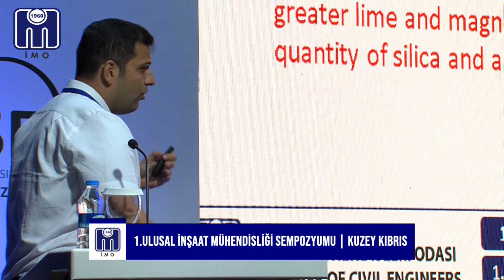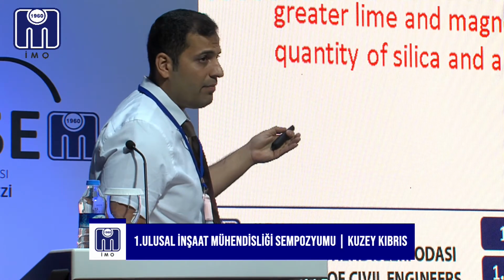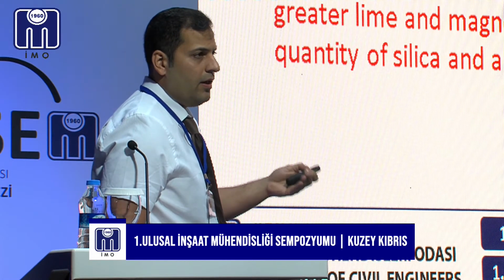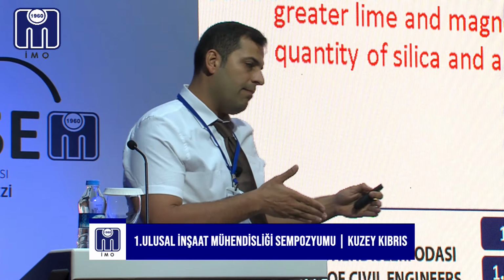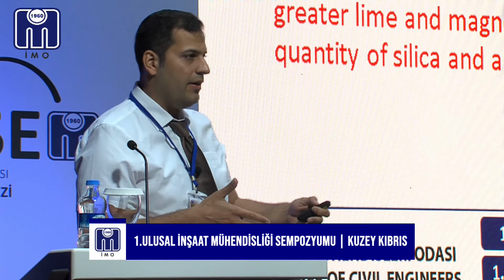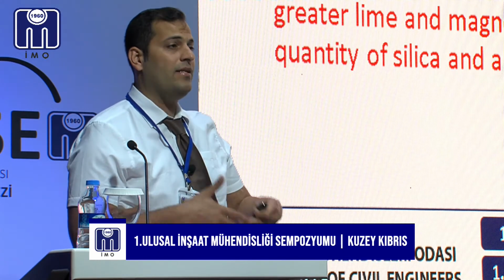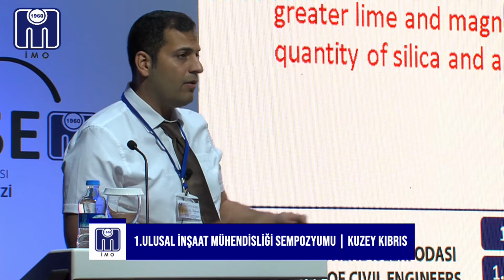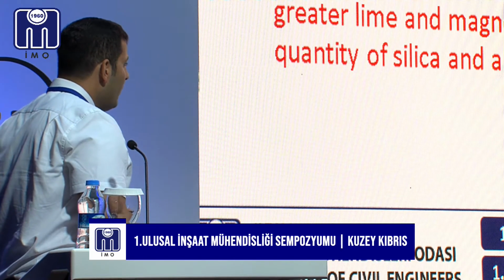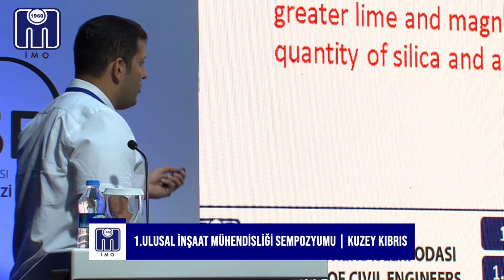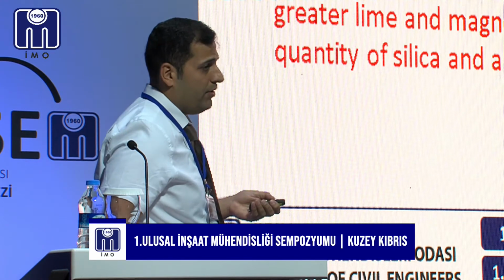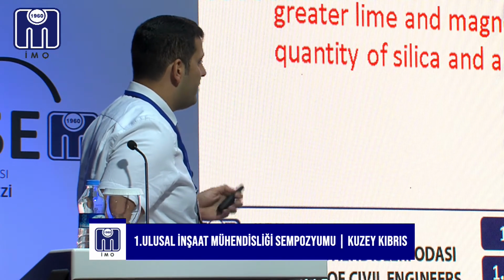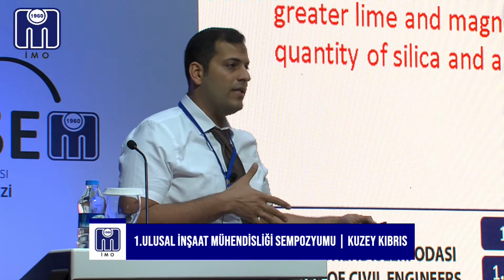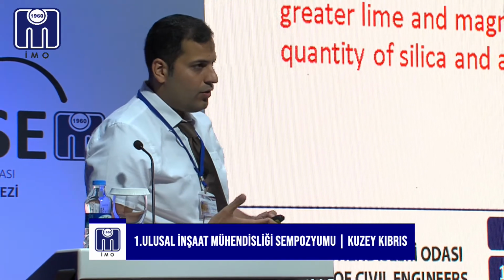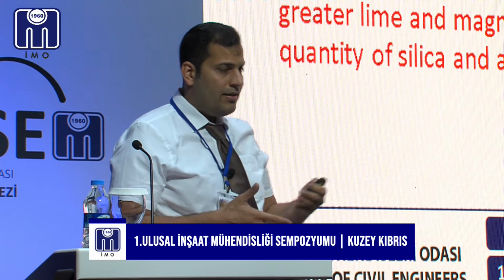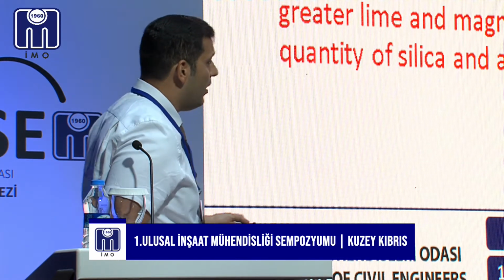Before going over the reasons, I would like to give very brief information about why marble dust and granite dust might be useful. First we should have some background and prove that this material will be useful in construction, that it could be a sustainable material in the construction sector, and then we could go over the reasons why they are not using it. Several studies show that marble dust has greater lime and magnesium concentration, while granite dust has greater quantities of silica and alumina. These are the basic materials we use to accelerate or produce hydration. So based on this chemical composition, these two materials might be useful in our concrete production.